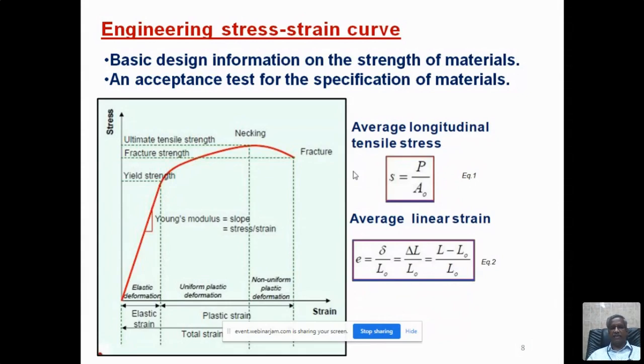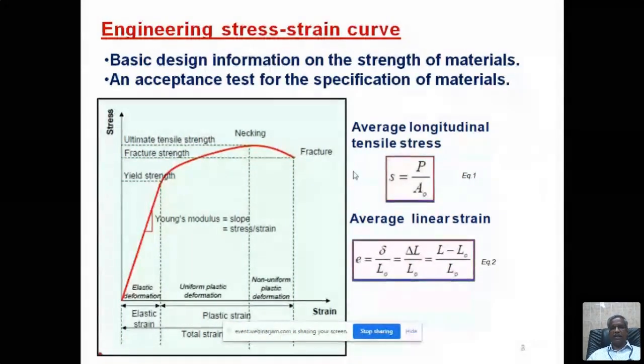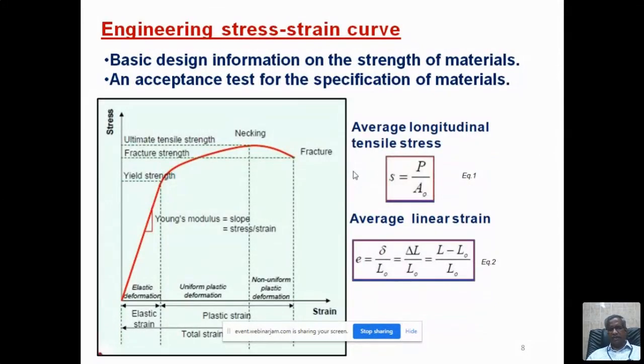If you know that initial cross-sectional area, and the maximum P is the maximum load that the material withstands before failure, then P by A is the average longitudinal tensile stress. Similarly, the average linear strain, because we are measuring the strain in the linear direction, not in the diameter direction, only in the length direction. So in the length direction, what is the initial gauge length? You take only the gauge length. People sometimes measure the entire length of the specimen. It is not required. You have to measure the elongation in the gauge length.